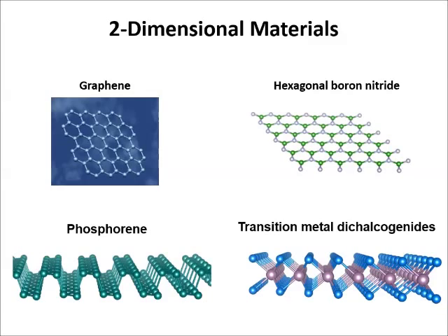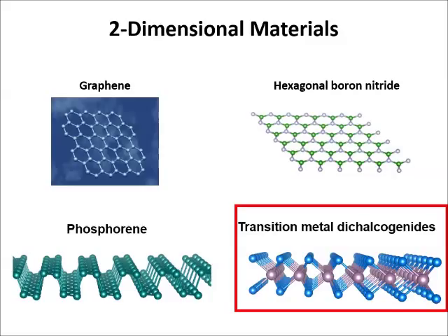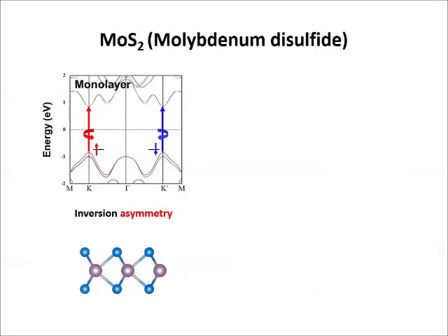Interestingly, the electronic properties of transition metal dichalcogenides are quite diverse depending on their crystal structure and layer thickness. Especially, MoS2 provides interesting physical phenomena, so called valley polarization. The valley polarization emerges due to the unique structure of the monolayer MoS2 that lacks the inversion symmetry.